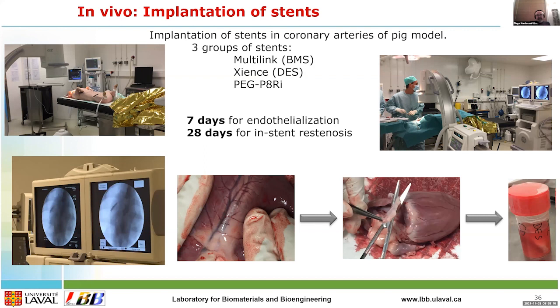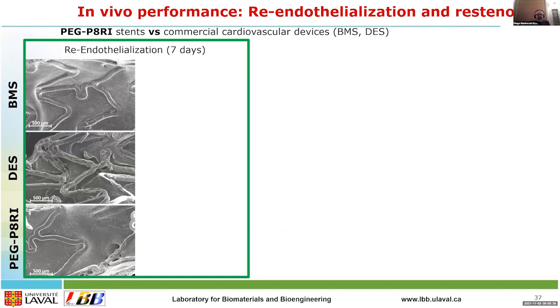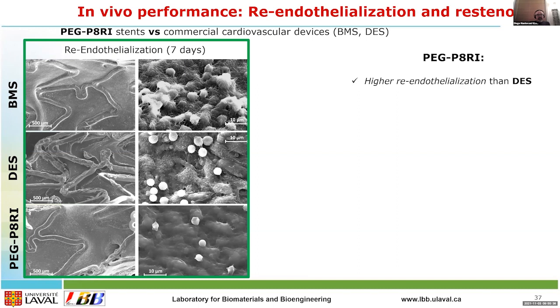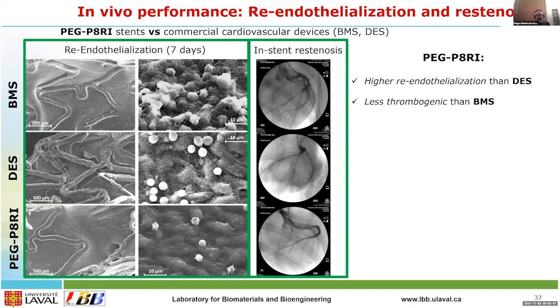So basically, these are the collected specimens, and in general, the in vivo performance is mentioned here. We took the bare metal stent, the drug-eluting stent, and the new PEG-P8RI stent, and you can see the reendothelialization at 7 days. You see here some platelets, but no platelets on the pegylated materials, and the restenosis by OCT. You can see where the stent is implanted. Basically, you can see it is patent. So the reendothelialization was higher than drug-eluting stent and less thrombogenic than bare metal stent.